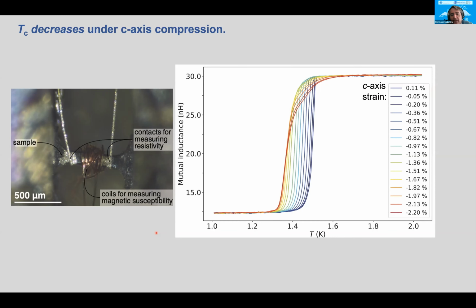And how do you explain the increase in the transition width? So the TC is very sensitive to in-plane strain. Just to be clear on the data, this is a susceptibility measurement actually. It's the mutual inductance of these coils, so we're measuring magnetic susceptibility. And right, what you're asking about is this tail. We seem to see this tail of increasing TC.